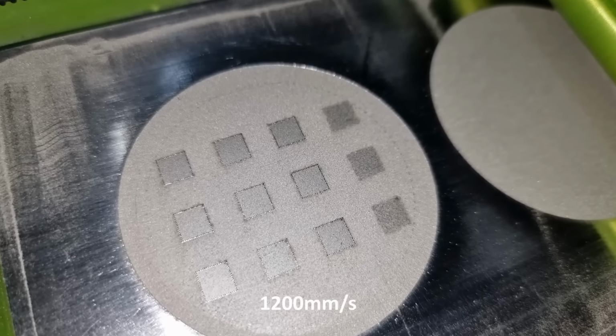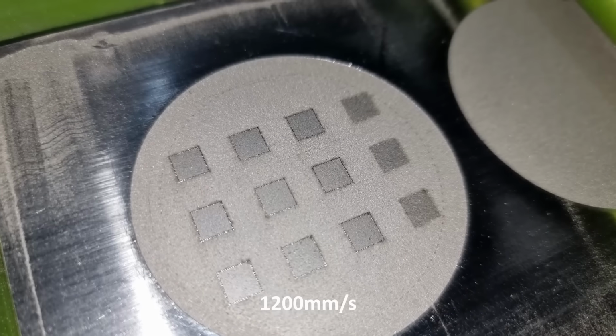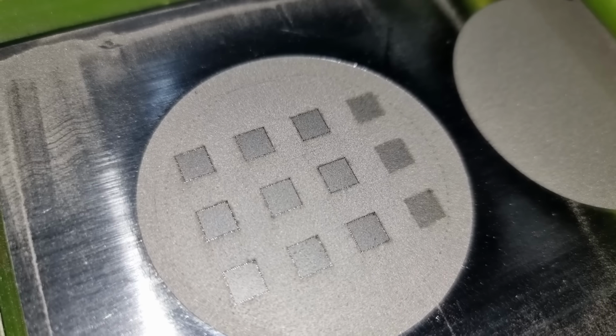I already knew from driving the process at 90mm per second I was expending far too much energy, causing an excessive droplet size. I had hoped that by driving the process at a much faster speed, I could iteratively sinter the metal until it had completely fused, avoiding the creation of spatter. What I discovered was that the process speed I had arbitrarily chosen was too fast, and instead blew the majority of powder out of the area to be sintered. Even though it was a failure, it came along with a couple of revelations.